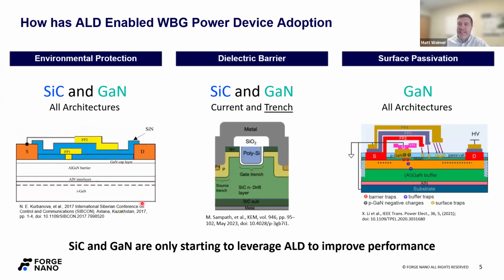And so here I'm just showing a nice GaN HEMT structure, just as an example of what we've coated with a moisture barrier to protect it from the environment. From our perspective and from what we've seen in the market, this is really applicable to both silicon carbide and GaN, and it's kind of architecture agnostic. We'll talk about the fundamentals of ALD in just a minute, but remember, ALD is a conformal technique. That means anywhere the gas can go, you'll get the same quality and same thickness of film. So with these little divots here, whatever features you have on your device, it will get the same amount of ALD, even down in these deep, dark corners.